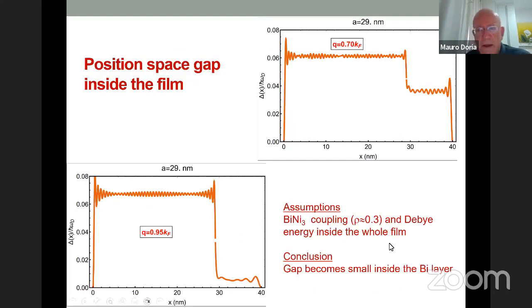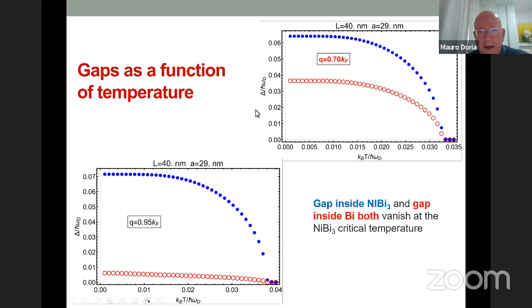So we take the equations that allow us to compute the gap, and that's what we obtained for these two cases: 0.6 for one potential barrier, and 0.7 of the Fermi surface, in 0.95. You see that when we do that self-consistent calculation, the gap is mainly on the nickel bismuth 3, but there is some gap living in the bismuth side. And in fact, if we look at the gap versus the temperature, we see that both gaps disappear at the same temperature, because they are coupled, but one is much weaker than the other.